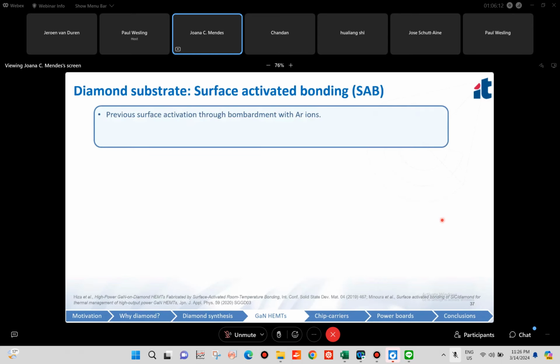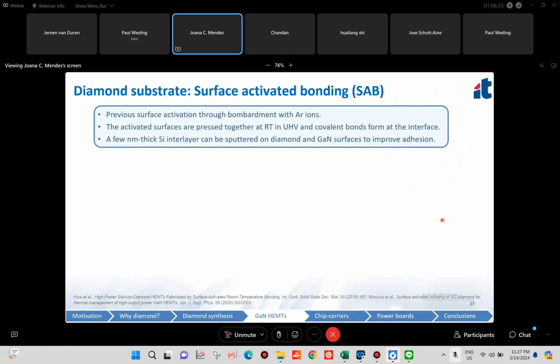To use the surface activated bonding, we start with both surfaces and we bombard them with argon ions. And this bombardment will create dangling bonds on both surfaces. And then when the surfaces are pressed together at room temperature in high vacuum conditions, these dangling bonds will convert into covalent bonds. And we can even use a few nanometer thick silicon interlayer to improve the adhesion if required.